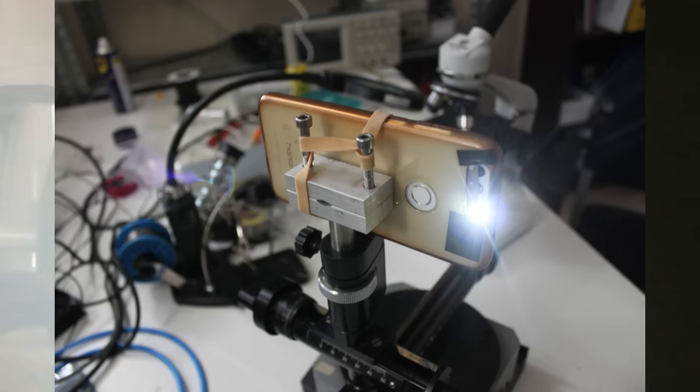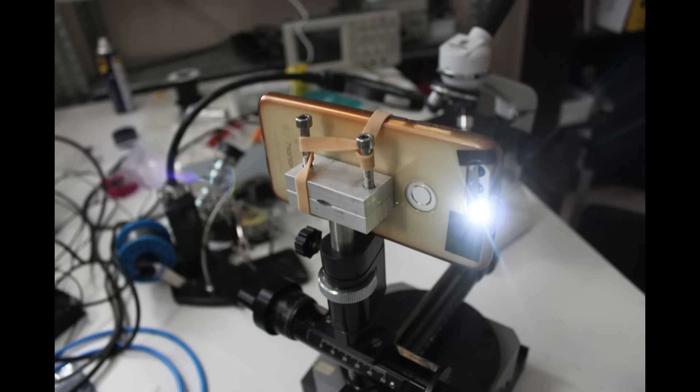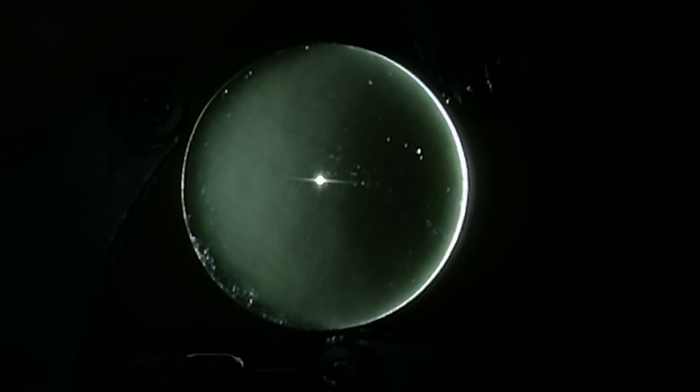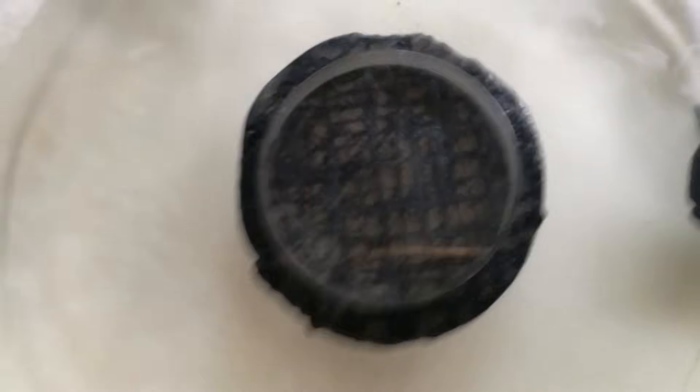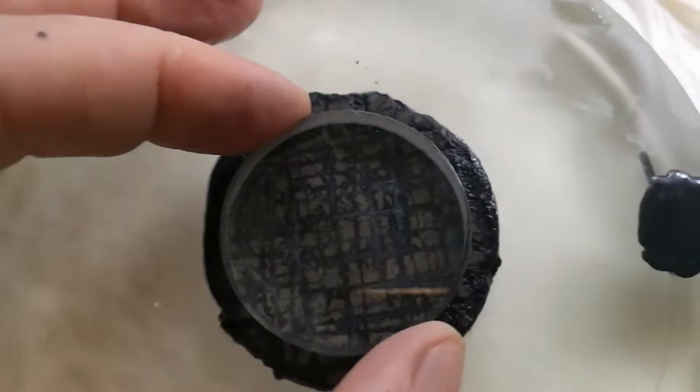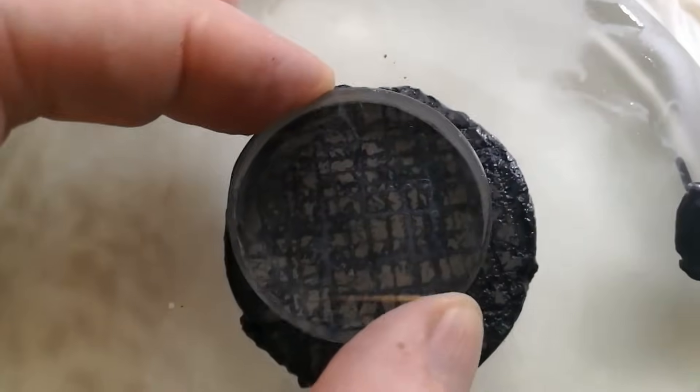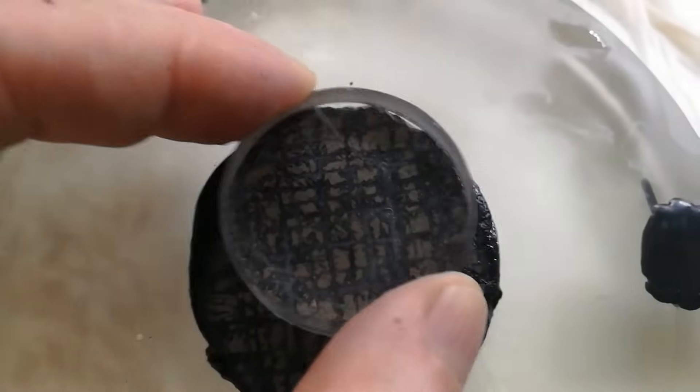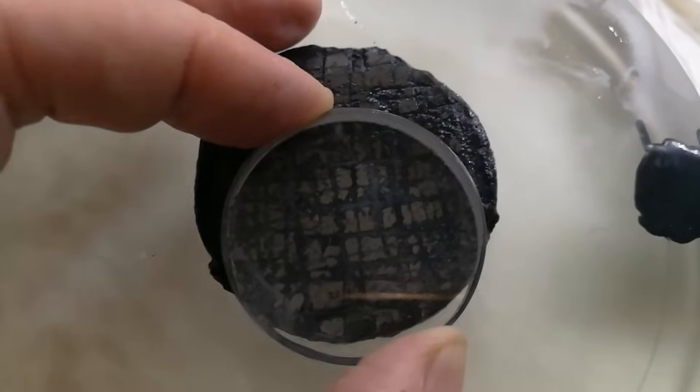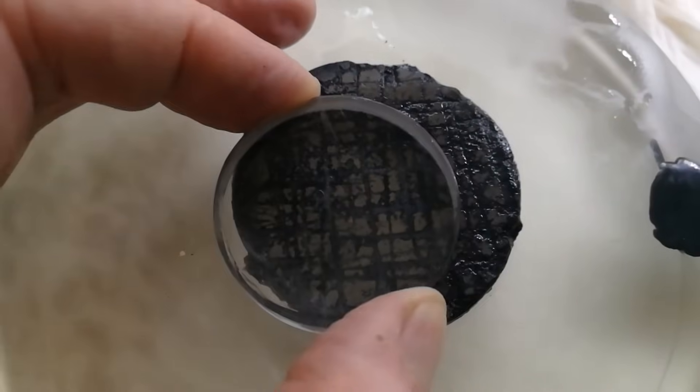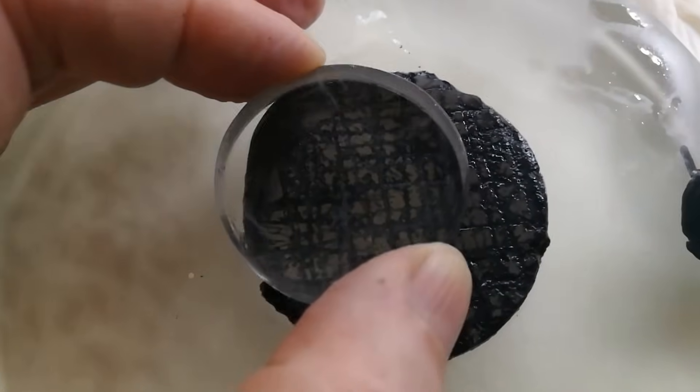Keeping the smartphone steady in the center of radius is a challenge, so here I place the phone on an adjustable stand. The Foucault image shows the presence of a turned-down edge, which is probably from temperature variations during the polishing process. However, it is not dramatic and can be fixed by additional and milder polishing, so using less pressure. Because this particular mirror is just intended for light collimation of an LED, I will leave it at this.